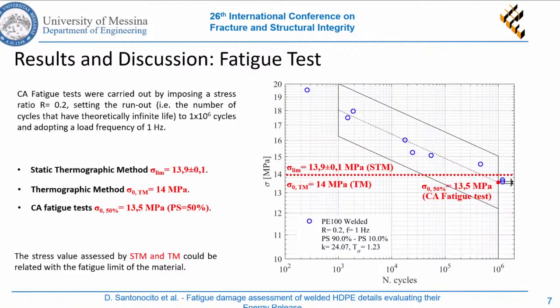At the end, traditional fatigue tests were performed, and as you can see from the last slide, we have practically equal values of the fatigue limit. The ones assessed by the static thermographic method and the thermographic method are near 14 megapascal, while the classical fatigue test with a probability of survival of 50% gives 13.5 megapascal. So at the end, we can assess in a very rapid way the fatigue limit of such material in a very short amount of time. Thank you.